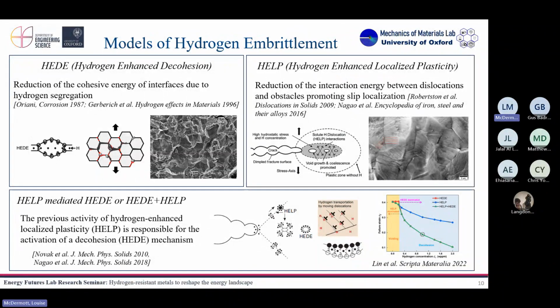But some people say that that's not enough to explain why hydrogen embrittlement takes place in many cases, and that there must be something else going on in the material. And then the second theory arises, hydrogen enhanced localized plasticity. It basically says that hydrogen is able to interact with dislocations during plastic deformation, and reduce the energy needed for dislocation mobility. It's not as simple as this. I'm trying to put it very simply and straightforwardly so you more or less understand. There are a lot of things behind it, but it's basically that. So in the end, according to this theory, hydrogen is enhancing your dislocation mobility, so you have localized plasticity around your crack.